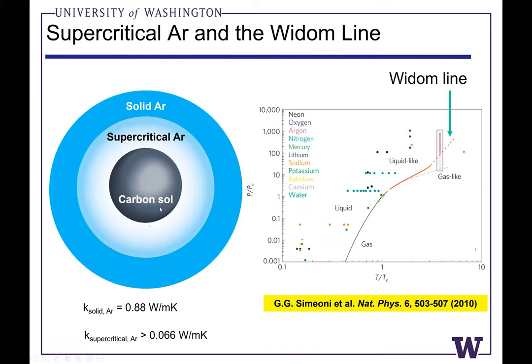And one very interesting physical property change is that when you go from solid, face-centered cubic argon at around 20 gigapascals, to supercritical argon at 20 gigapascals, the thermal conductivity drops by at least one order of magnitude. So we're hypothesizing that effectively we're fluidizing the argon into a supercritical fluid. These atoms rapidly diffuse into the carbon target material. And then once the diamond lattice forms at these extreme conditions, it's trapping those atoms inside the diamond crystal. And then we can recover those samples.